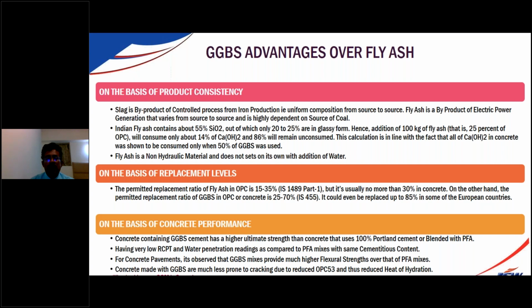And replacement levels: you can replace up to 35% maximum with fly ash. The quality is very good, but generally people are going with 30%. On the other hand, if you are using GGBS, you can go up to 70%. There are instances where people have used up to 85% for many applications. In Karnataka, at the Karwar Seabird project, where they are doing piling, Larsen and Toubro are going up to 70% for grade M55. So that is amazing, because they have found the benefit of using the product in terms of performance, mainly durability.